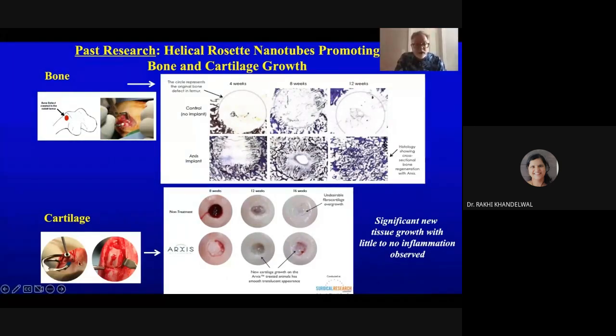Similar for cartilage, creating a defect in rabbit cartilage around the knee joint of the rabbit. Here for the non-treatment, we ended up getting fibrocartilage without using a material. Using our material, we end up regenerating cartilage after about 16 weeks. In all of these cases where we've used this material to regenerate tissue, we see little to no inflammation. One thing you remember about COVID-19, it often induces a lot of inflammation. So we were intrigued, again, to use this material to attach to the virus, keep it from replicating, and also reduce inflammation that occurs with COVID-19.